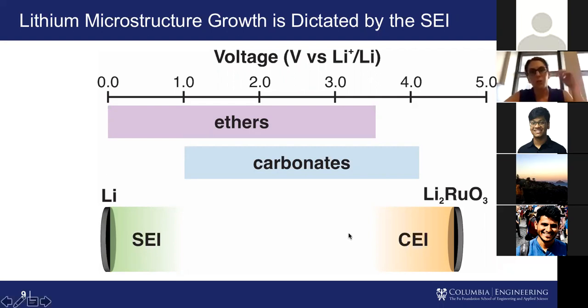The main issue with all batteries is that the electrolyte that you use is suspended in this carbonate solvent. And this carbonate solvent is not electrochemically stable at the operating potentials of your anode or your cathode. What I'm showing here is basically the window in which the carbonate electrolyte that's used in commercial lithium ion batteries is stable to operate in. You can see it has a lower cutoff voltage of about 1 volt.